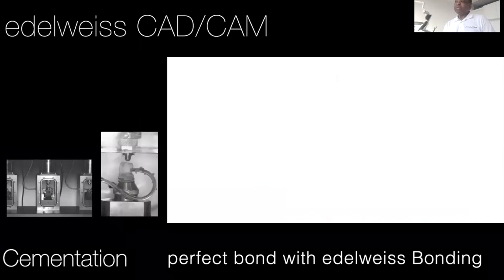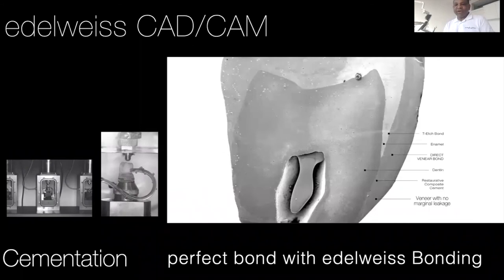Because it becomes one single unit, there would be no sub-margination or margin ditching, and therefore stain-free margins. There will also be no color mismatch between the resin cement and the restoration. We tested the system using a chewing simulator together with thermocycling and found a perfect bond between the tooth and the restoration on both the enamel and the dentine side, with no marginal leakage.